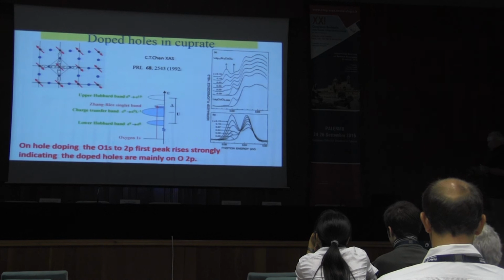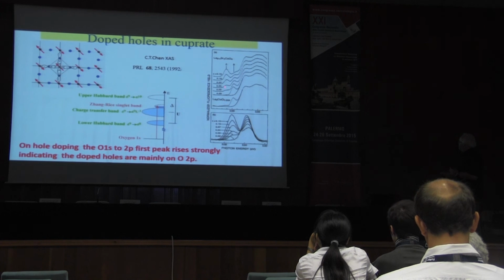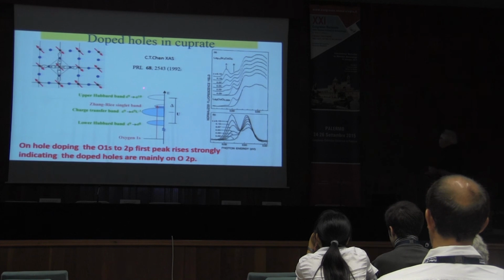I would get some copper 3+. But actually, X-ray absorption tells you on the oxygen edge that you have this pre-edge peak, which goes up in intensity very, very strongly as I replace the lanthanum with strontium, and that really is a very strong indicator that the holes, when you dope with strontium, go mainly on oxygen and not on copper. Okay, so that already changes your starting point of the doped system.